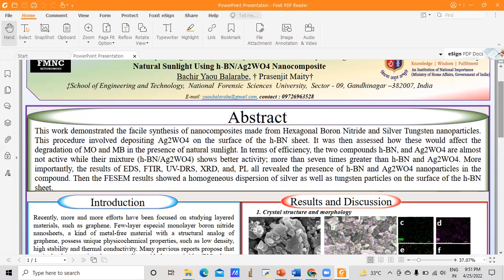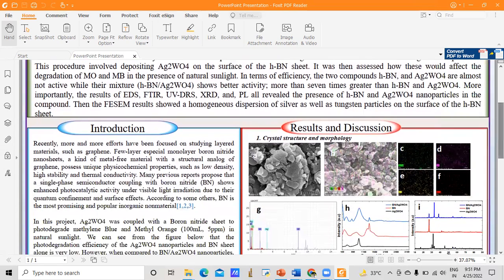natural sunlight. And here, in terms of efficiency, the two compounds, either HBN or Ag2WO4, are almost not active, while this mixture of HBN and Ag2WO4 shows better activity. More importantly, the results from EDS, FTIR, UV-DRS, XRD, and PL all reveal the presence of HBN and Ag2WO4 nanocomposites in the compound. Then the FESEM results show a homogeneous dispersion of silver as well as tungsten on the surface of the HBN sheet.